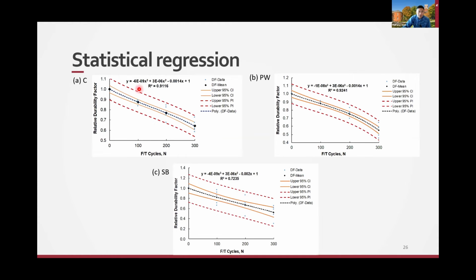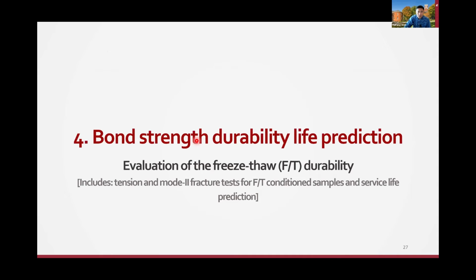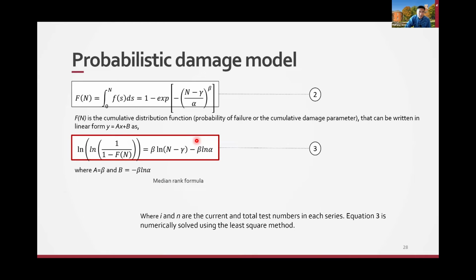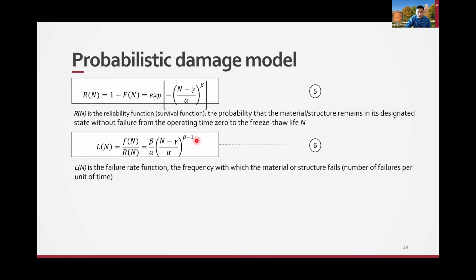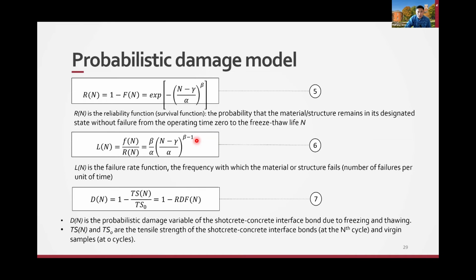And you can try to fit the curve a little bit using different models, polynomial or other ways, so you can do some statistical analysis. What we would like to know is how long the bond can survive the weathering. So we feed the data into this probabilistic damage model to try to quantify the relationship between the freeze-thaw cycles and the bond deterioration.